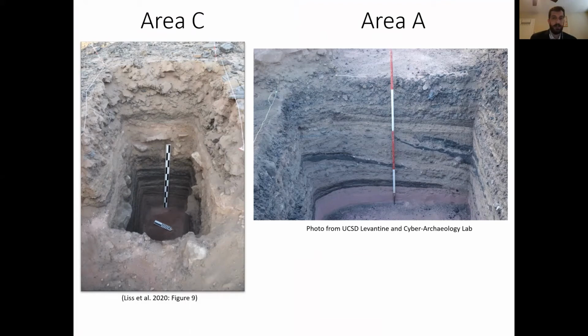I do want to compare the 2 slag mounds from Area C and Area A briefly. Overall, the stratigraphy was fairly similar: crushed slag above bedrock, some domestic and habitation refuse, and then a thick accumulation of slag in the surface layer. But where they differ is in this initial layer of crushed slag. As I had mentioned, this was somewhat thin at Area A with 5 to 10 centimeters of crushed slag, whereas in Area C, we had almost 80 centimeters of crushed slag directly on bedrock. So we believe that this suggests the site was producing fairly substantial copper immediately from its establishment.